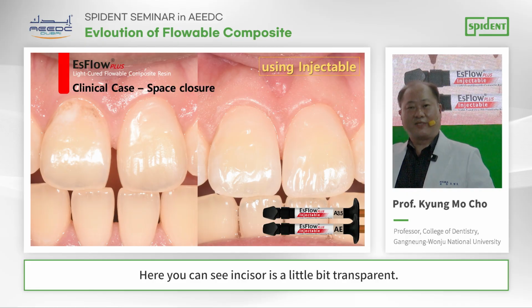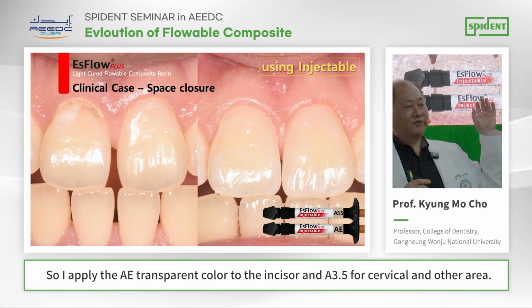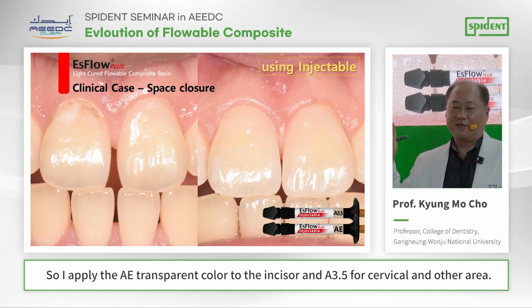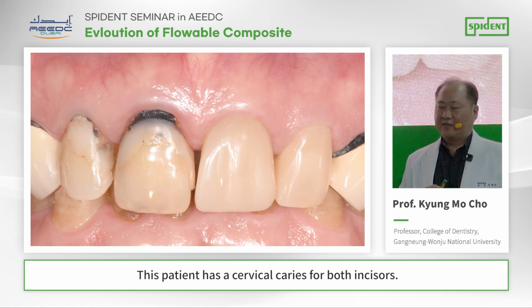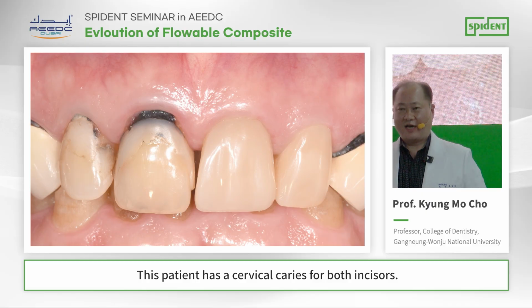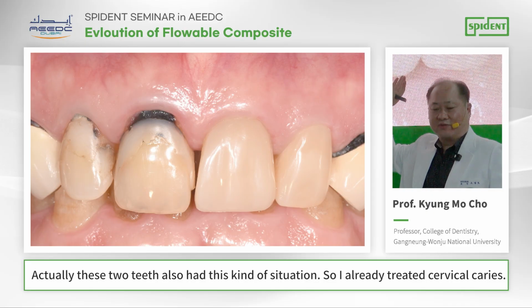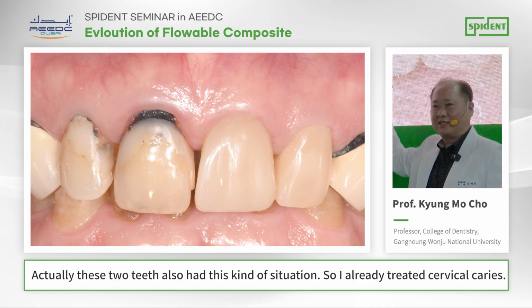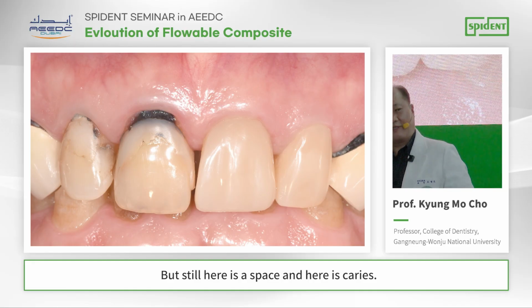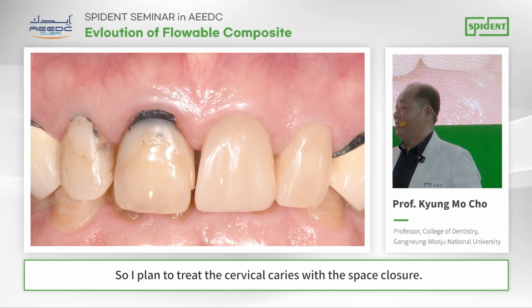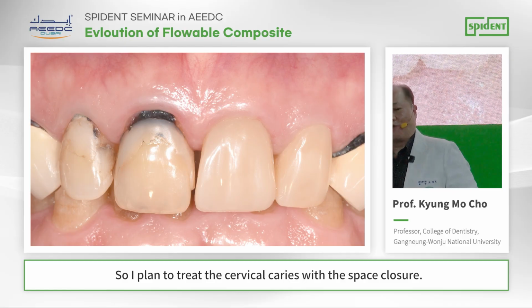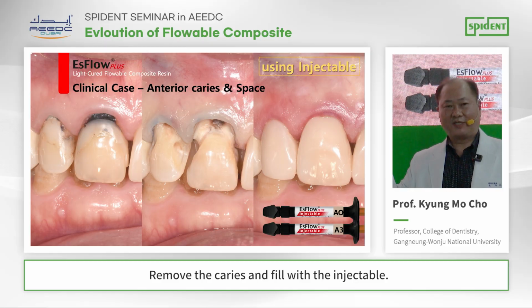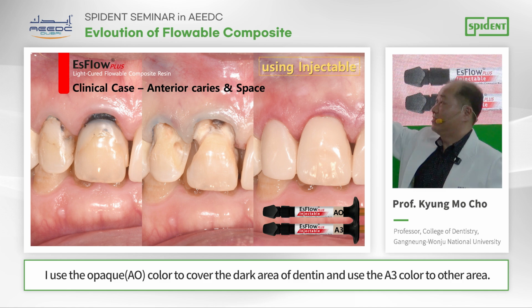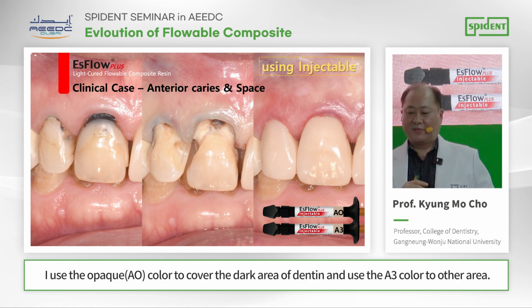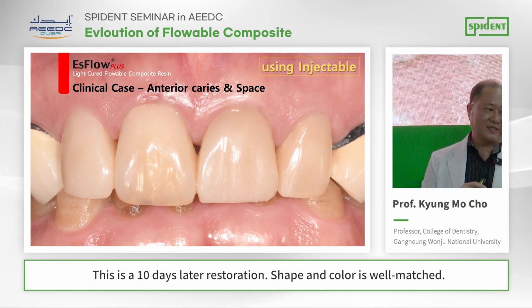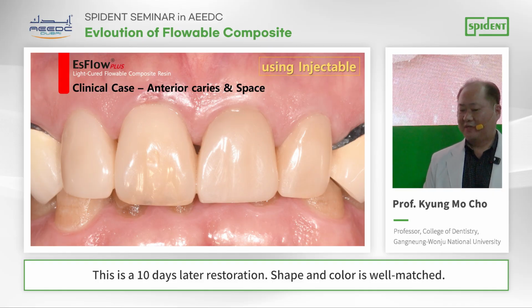Here you can see the incisor is a little bit transparent. So I applied the enamel transparent color to the incisor and A3.5 for the cervical and other areas. This patient has cervical caries for both incisors. Actually, these two teeth also had this kind of situation. So I already treated the cervical caries, but still here is a space and here is caries. So I planned to treat the cervical caries with space closure, remove caries, and then fill with the injectable. I used the opaque color to cover the dark area of dentin and used the A3 color for the other area. This is the restoration 10 days later. Shape and color are well matched.